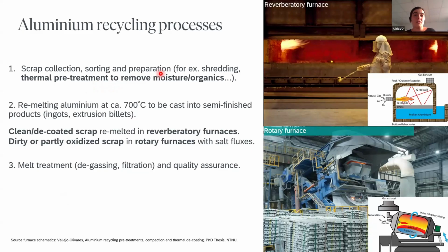But then there are certain steps to prepare the aluminum scrap for melting. This can include shredding, sieving into different sizes, and also depending on the type of scrap and the level of contamination and the type of furnace that is available, sometimes it's possible to heat up the scrap in order to burn off the moisture and the organics present. This is known as a thermal pretreatment. And then aluminium is melted at around 700 degrees Celsius.